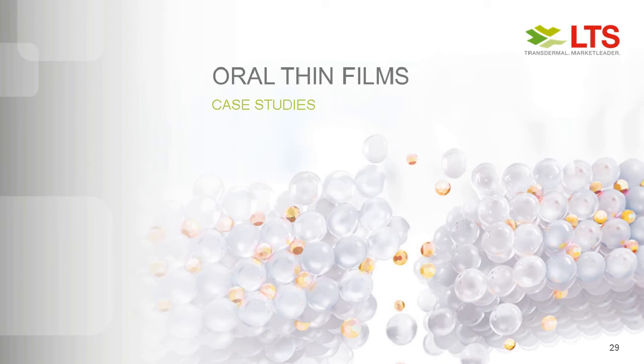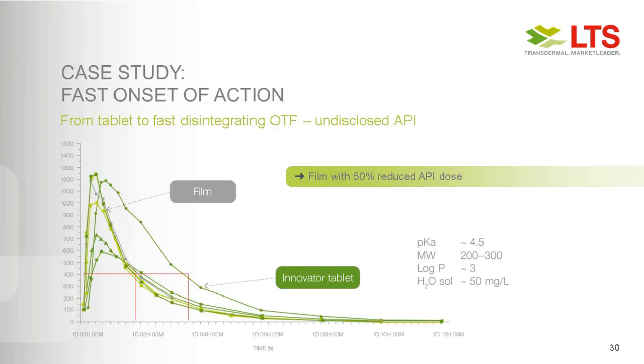So, and I think from here on, we have a number of case studies which we would like to present on our thin films, and to show you the different advantages which can be achieved by this dosage form. The first case study is focusing on the fast onset of action. Especially, this one was an API which was already available as a tablet formulation from the innovator, and we have worked with the innovator in this case, and we have transferred this into different film formulations. So you can see here by the PK profile that there's one innovator tablet, the green curve, and there's a number of OTF film formulations which have been tested in a clinical trial and in a clinical setup.